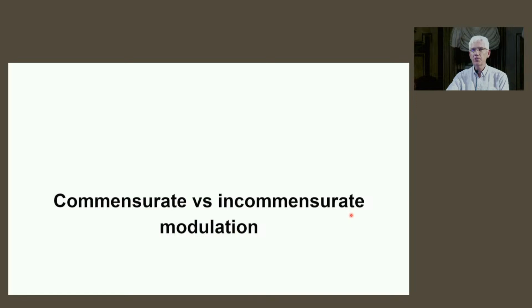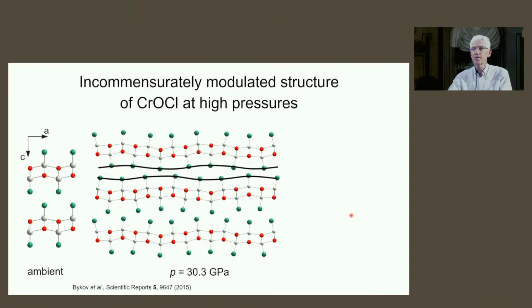Yeah, one issue which sometimes comes up and actually is quite important, is it a commensurate modulation like a 5-fold supercell, or is it really incommensurate with an irrational number for this sigma, for this Q vector? And I like to illustrate the problem with chromium oxychloride. It's orthorhombic, you can see on the left, and under pressure it becomes all wavy. And with the black line I highlighted the wave, maybe you can estimate some wavelength. And the reason is that these chlorine atoms at high pressure fill up better this van der Waals gap when they are modulated.